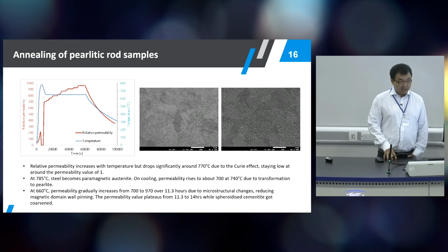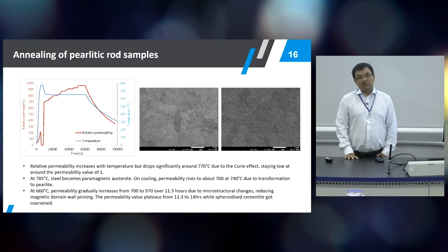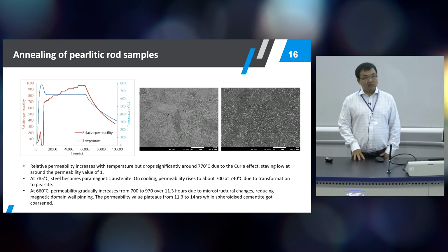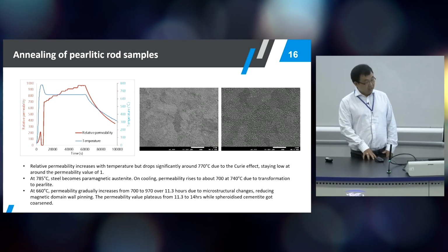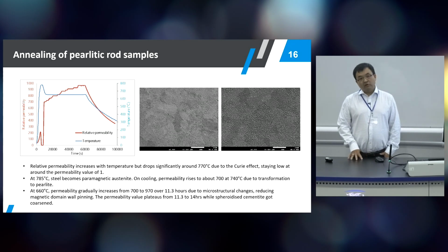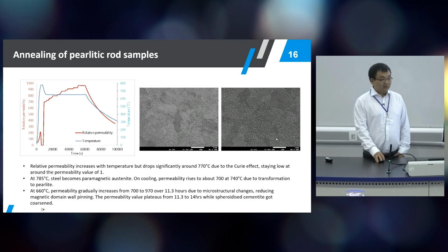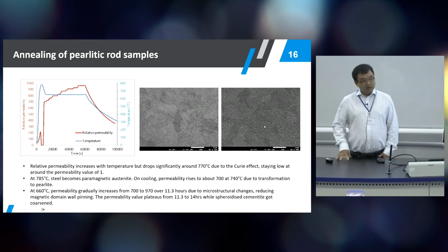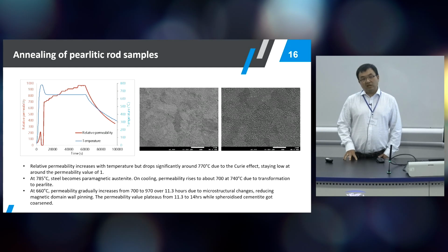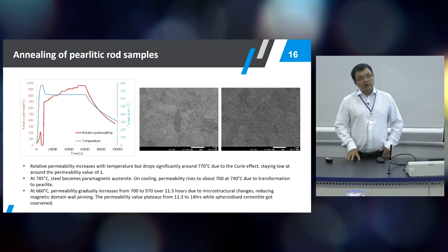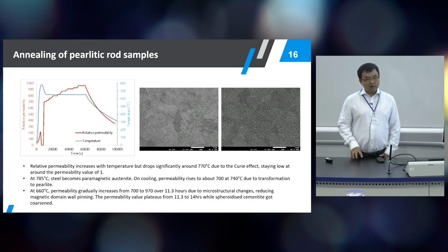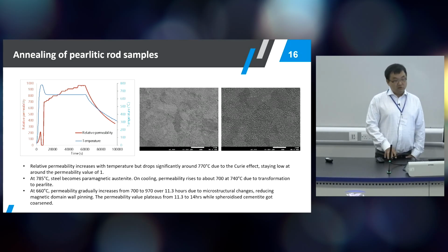The other application where we tried this type of sensor is for rod steel. So this is a pearlitic grade where we deliberately wanted the pearlite to fully spheroidize into this kind of fully precipitated microstructure. There is a heat treatment specially designed to achieve this microstructure, but currently the industrial partner is soaking the material for a period of time, whereas the sensor can potentially look at how the sensor signal changes. In this case, we can see when the microstructure is changing from pearlitic structure to fully spheroidized structure.